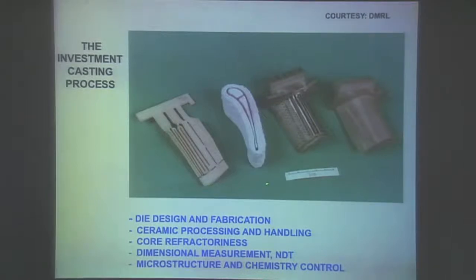You're pouring nickel at 1400 degrees centigrade, and you're meeting complex aerofoil shapes with dimensional tolerances of a fraction of a millimeter. And you're pouring this hot metal into a ceramic system. Imagine the thermal distortions that this ceramic core, ceramic shell, and metal undergo as it cools down in this complex shape. And you have to design your die to engineer the corrections due to these thermal distortions to get the final control of a fraction of a millimeter of tolerance on the final shape.